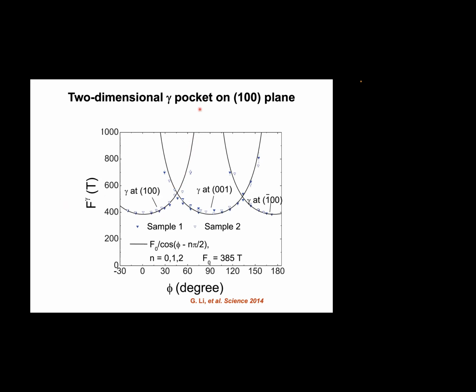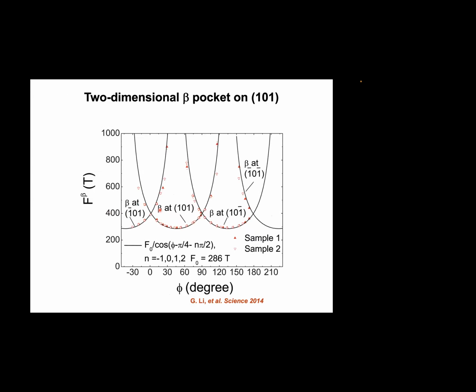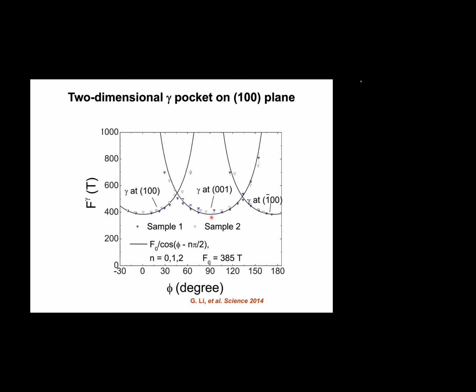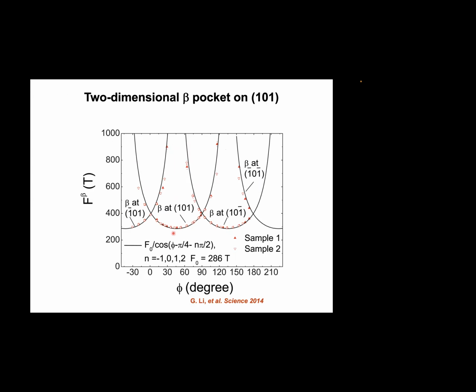These diverge, eventually we will not be able to observe that because it will be gone. But because it's from neighboring facets that are 90 degrees away, we will still have the oscillation in those angles, just coming from a different branch. This is coming from one set. The other set also follows the dispersion. Sorry, I forgot to mention, this is a 1 over cosine angle dependence with minimum here at 0, 90 and 180 degrees, whereas the other is from 45 and 135 degrees, which means that, as I emphasized before, it's a cylinder-like Fermi surface with minimum happening exactly in the other family of the facets.